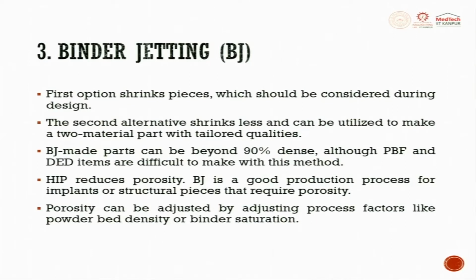So, I have clearly stated the distinction between sintering and infiltration, which happens depending upon your requirement. And when the copper is fed in, the copper's or the bronze's viscosity is very important, such that it can have a capillary action into it. And having capillary action is also very tough because the pore sizes are small and it is metal. So, you need to have a very high negative pressure. Generally, it does not happen so easily.